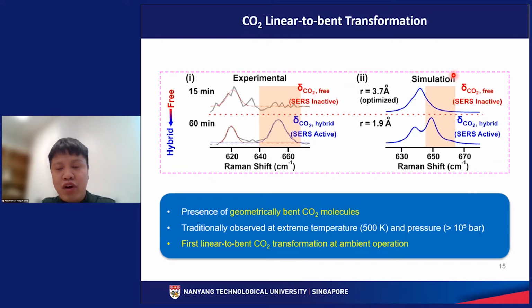Collectively, this comparison tells us that geometrically bent CO2 molecules are present near our silver nanocube surface. One point to note is that for CO2 to adopt a bent geometry, it usually requires a very extreme temperature of 500 Kelvin and high pressure of 10,000 bar. In our case, we are able to achieve this at ambient operation of 1 bar and 298 Kelvin. Therefore, our work shows the first linear to bent carbon dioxide transformation at ambient operation. This is important because we are trying to create a pseudo high pressure microenvironment right at the interfacial cavity, where molecules can be concentrated into a quasi-condensed phase very near to the functional solid platform, like a catalyst, or for our silver nanocube.